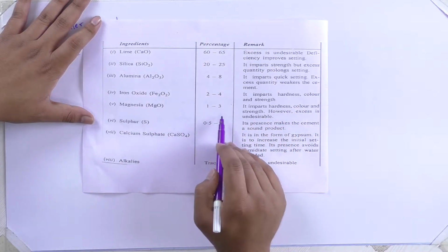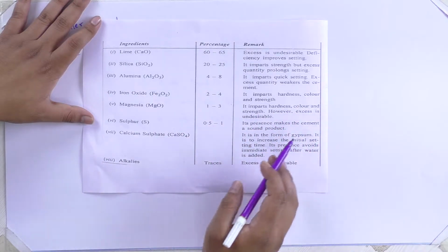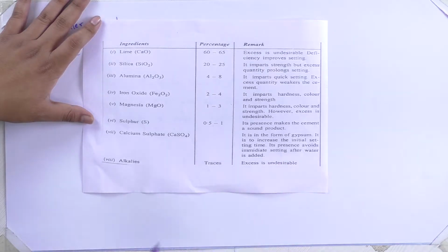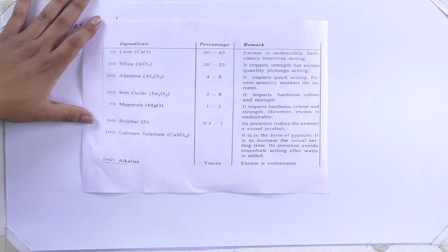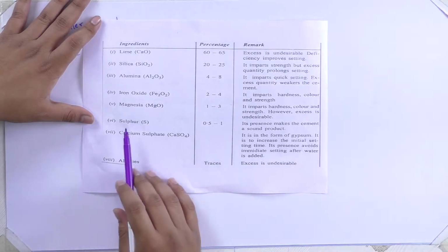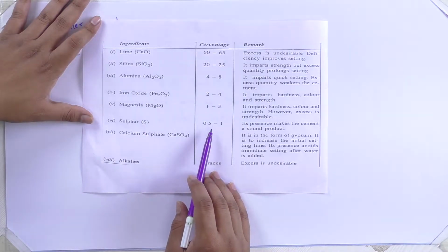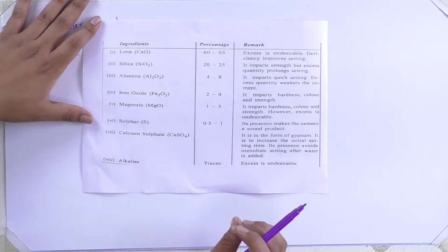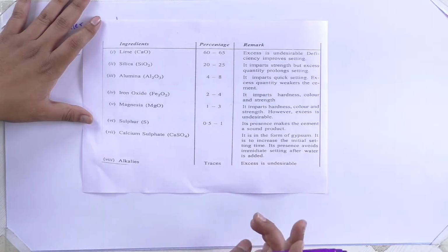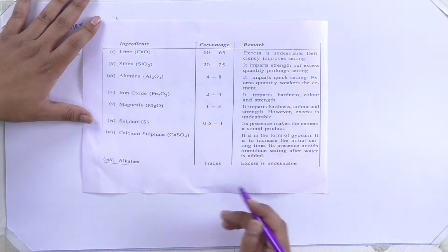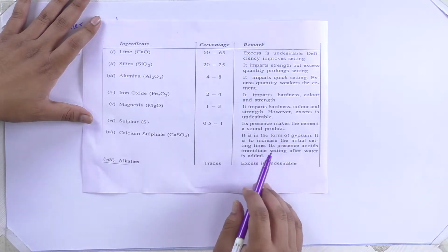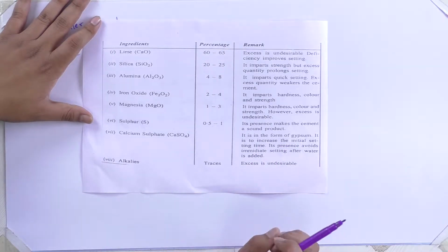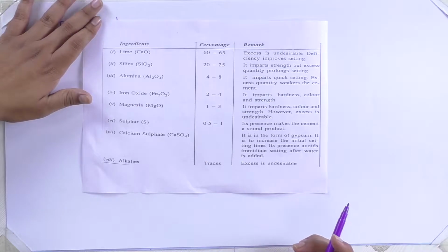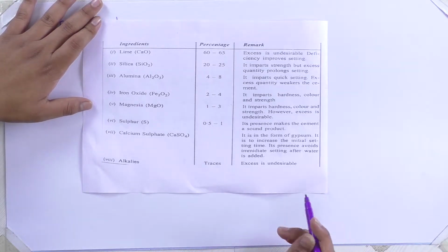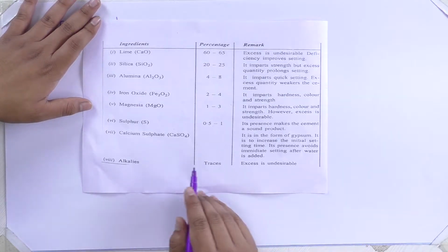Magnesia in 1 to 3% imparts hardness, color and strength, however the higher quantity is not acceptable here. Sulfur we use in 0.5 to 1%, and calcium sulfate of 0.5 to 1%. Its presence makes the cement a sound product, and calcium sulfate is in the form of gypsum. It is to increase the initial setting time, and its presence avoids the immediate setting after water is added. And alkalis are used in trace amounts.